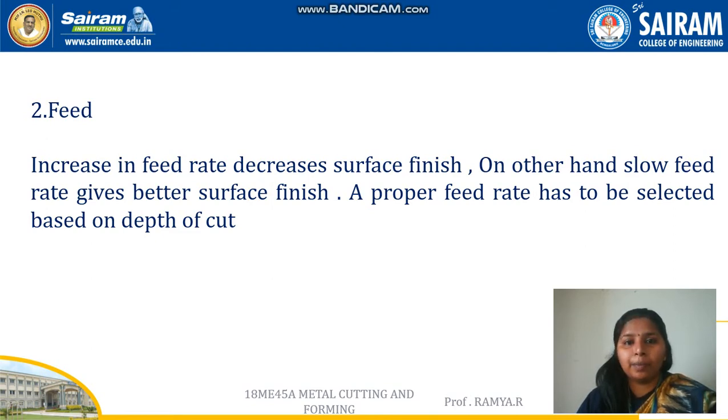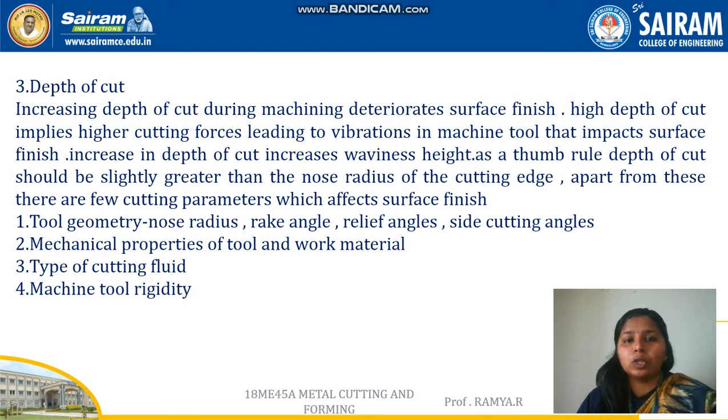The next parameter is depth of cut. Increase in depth of cut during machining destroys the surface finish. High depth of cut implies high cutting forces leading to vibrations in the machine tool that impact surface finish. Increase in depth of cut increases the waviness height. One of the failures in the surface is waviness. As a thumb rule, depth of cut should be slightly greater than the nose radius of the cutting edge.